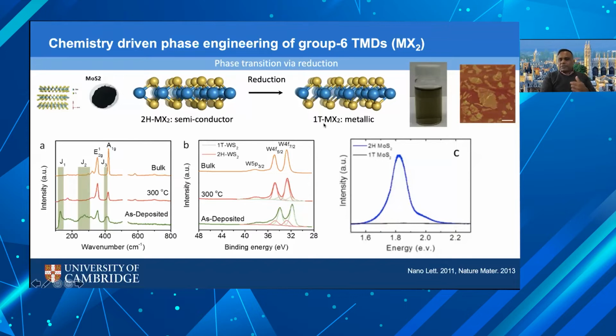The chemistry of the phase transformation is something that we've published quite a bit on, but very briefly, we have this additional electron from the lithium that goes onto MoS2, into the d orbital of the molybdenum specifically. And to accommodate this additional electron, there is a structural change that happens, that is from the 2H phase to the 1T phase. And you can monitor this with Raman spectroscopy. So here, as deposited means after we've done the chemical exfoliation, we take individual sheets of MoS2 that are now in suspension, we deposit them onto a substrate and we measure the Raman spectrum. And what we see is the appearance of these J1, J2 peaks, which are characteristic of the 1T phase.